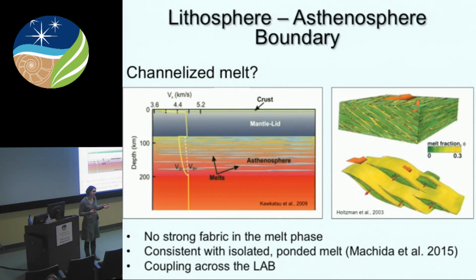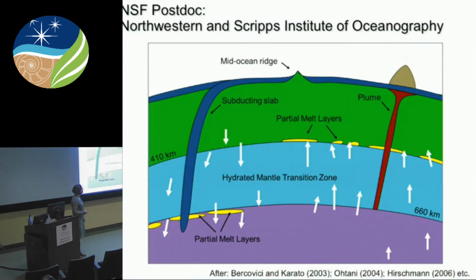Furthermore, in the Western Pacific, there have been geochemical observations of what's known as petit-spot volcanism. What they have been able to show is that the volcanic systems are tracking with the plate motions. They seem to be very isolated, and so what they've proposed is that these are isolated melt ponds that are basically trapped between the lithosphere and the asthenosphere, which means that there's strong coupling at the LAB. We don't have these large, sheared, interconnected melt films, at least not in the Western Pacific at the LAB.